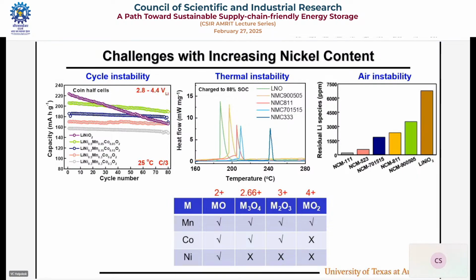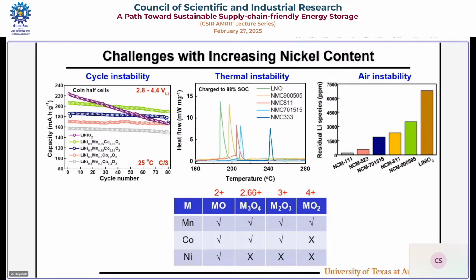Third, nickel 3 plus is not very stable in air. Lithium comes out to the surface. It forms lithium hydroxide, lithium carbonate. That is called residual lithium. That's basic. If it is, when they make electrode, there will be a lot of clogging. They cannot make good electrode. Headache. This number has to be less than 2000 parts per million. So these three problems. Is it strange?